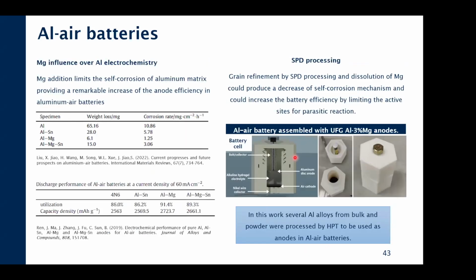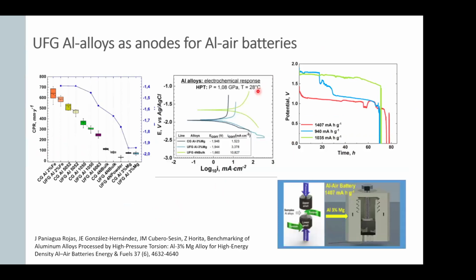So just to summarize, we tried the standard aluminum magnesium, which is one of the most important prototype systems for this kind of batteries. And in collaboration with the University of Costa Rica, we assembled them into some nice battery cells. We produced the aluminum anodes by high-pressure torsion, and these aluminum anodes are placed into a potassium hydroxide gel electrolyte and an air cathode that we buy commercially, and we test this battery prototype in the potentiostat, and we get the corrosion. So we did see improvement with grain refinement, not so much in bulk commercial alloys, but adding 3% magnesium was one of the best.